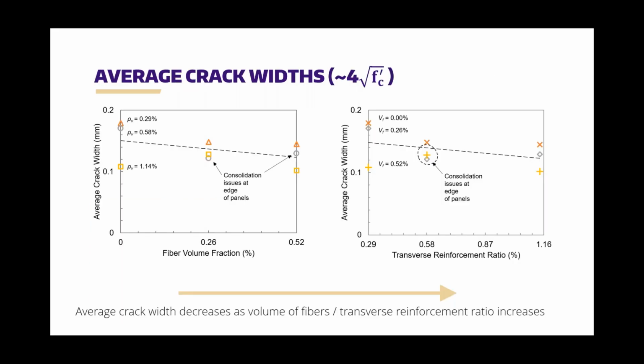So some of the things that you'd hope for in terms of the addition of fibers, you'd expect that the crack widths would decrease as you add fibers. And so first I was going to show you average crack widths. So here's the average crack width as a function of both fiber volume fraction, the plot on the left, and as a function of transverse reinforcement ratio with the plot on the right. And as you can see, in both cases, the average crack width decreases as the volume of fibers or the transverse reinforcement ratio increases. And so you can see there's a few data points there that look a little weird.